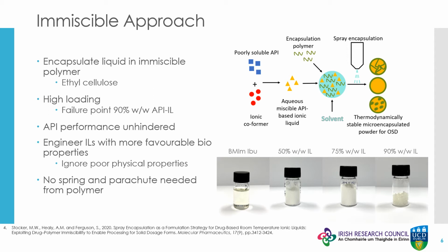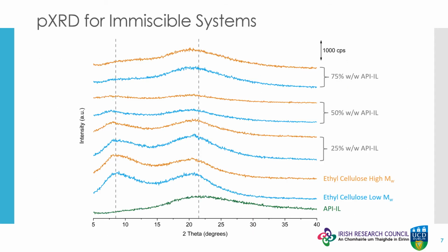This is advantageous as there is no so-called spring and parachute effect required from the carrier polymer, as would be expected in an amorphous solid dispersion, so it demonstrates that the stability and solubility enhancements are thermodynamically stable as opposed to kinetic. As with the miscible systems, PXRD was used to ascertain whether the liquid form of the API afforded by the IL was preserved during the spray drying process for the immiscible systems. Again, the diffuse halos and absence of Bragg peaks confirm this for both grades of ethyl cellulose and for all ratios of API-IL to polymer studied.